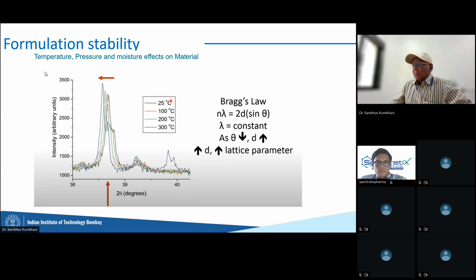Yes. And also another cool thing that we can see here is that at higher temperature, something new formed in your sample, which showed up. Some new chemistry happened, which is also observed. So that's essentially what we can study using XRD at higher temperature. Similar things can be seen under vacuum, at higher and lower moisture content and things like that. So the moisture part of this is very critical.